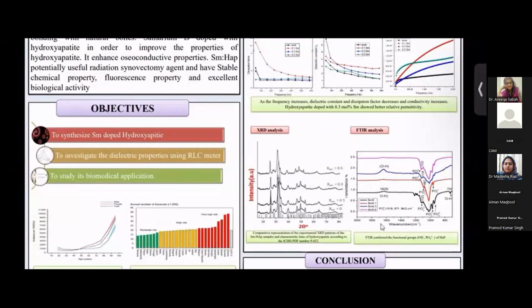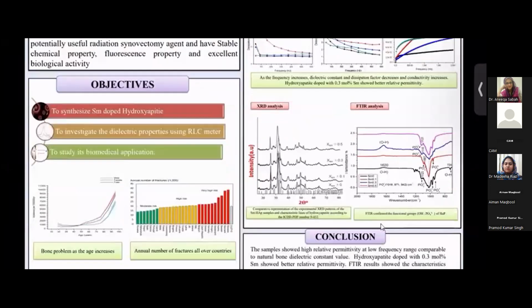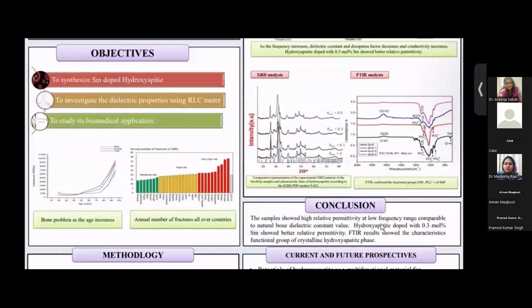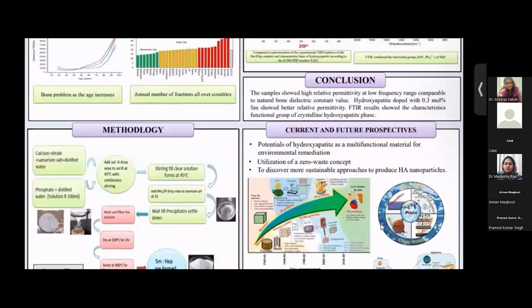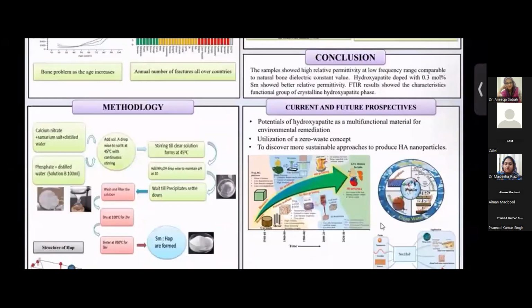Conclusion. The samples showed high relative permittivity at low frequency range, comparable to the natural bone dielectric constant value. Hydroxyapatite doped with 0.3 mol percent samarium showed better relative permittivity.